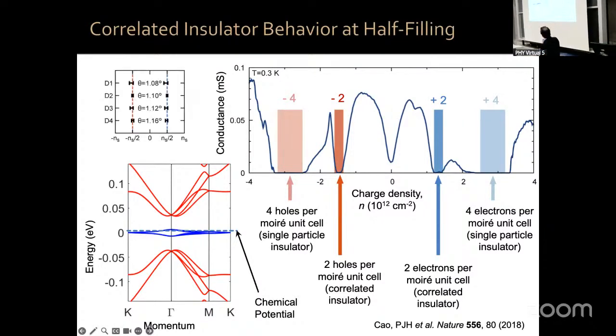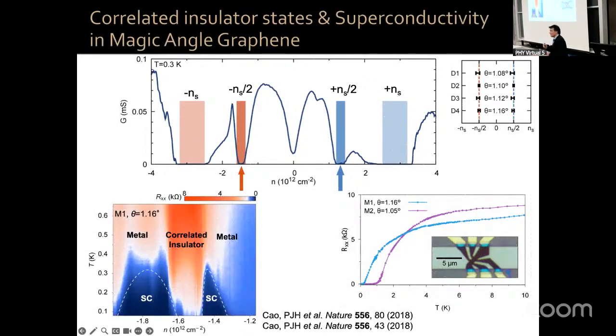And well, just in case turned out to be true, and we discovered superconductivity in this system. So when you dope a little bit away from the correlated insulator, you have an electrically tunable superconductor, okay?